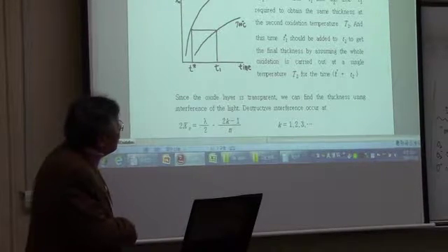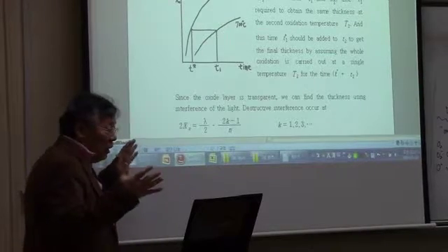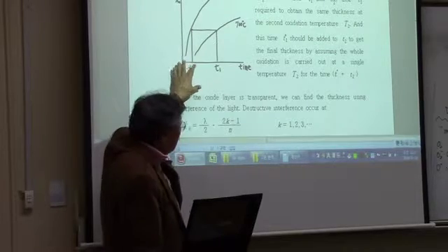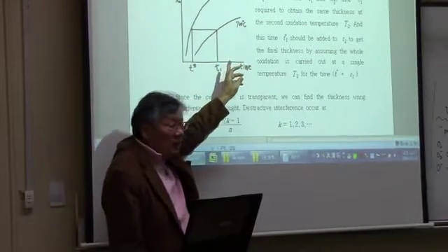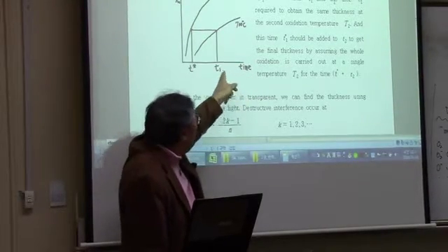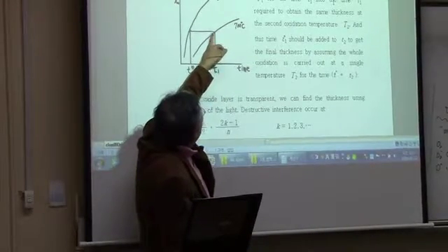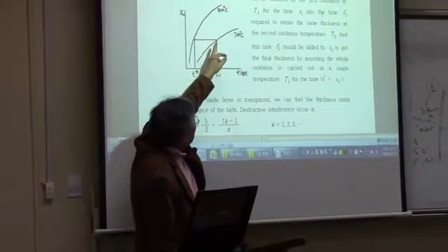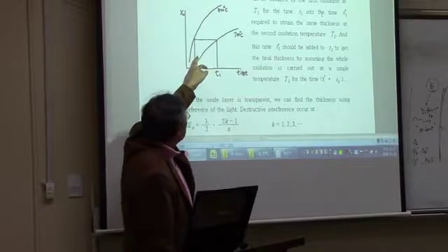And to answer that, what you have to do is you just come to the table or the figure, and firstly you did a 700 degrees centigrade wet oxidation for 1 hour, then you end up with a time corresponding to the 800 degrees centigrade dry oxidation process.